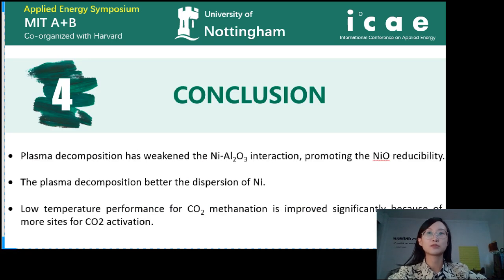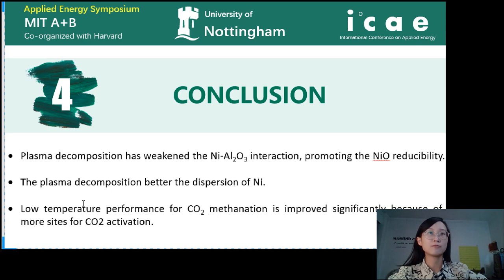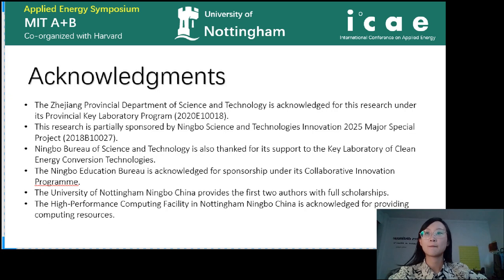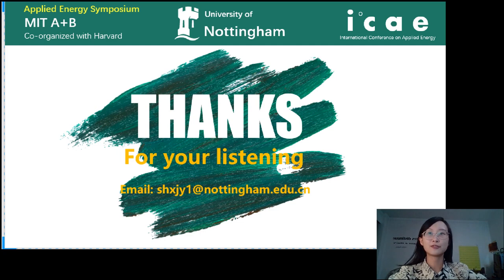Now we come to the conclusion. We found that plasma decomposition has weakened nickel-alumina interaction, promoting the nickel oxide reducibility. Plasma decomposition also improves the dispersion of nickel. The low-temperature performance for carbon dioxide methanation is improved significantly because of more active sites for carbon dioxide activation. Thanks for the funding from Zhejiang Province and Ningbo City, and thanks for the scholarship from the University of Nottingham. Also, thanks to my supervisor Dr. Tao Wu for his guidance. Thank you for your time and feel free to contact me.